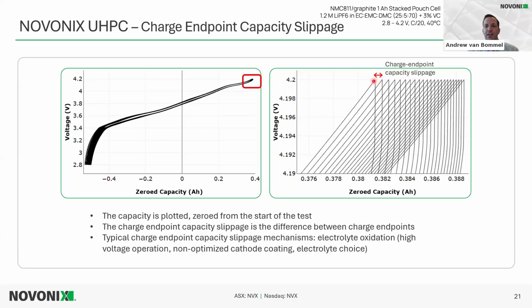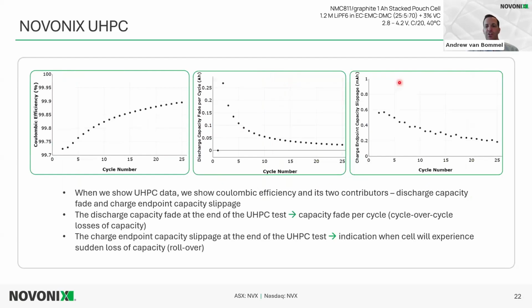And this is because there's some oxidative processes that are causing this charge endpoint to walk along. And the difference between one endpoint and the next is the charge endpoint capacity slippage. And as I mentioned, this can be due to things like electrolyte oxidation. Sometimes this can happen because we have higher voltage operation. We might have a non-optimized cathode, like a poor cathode coating, and then also electrolyte choice could enable this to walk along. So using these two metrics gives us a lot of insight.